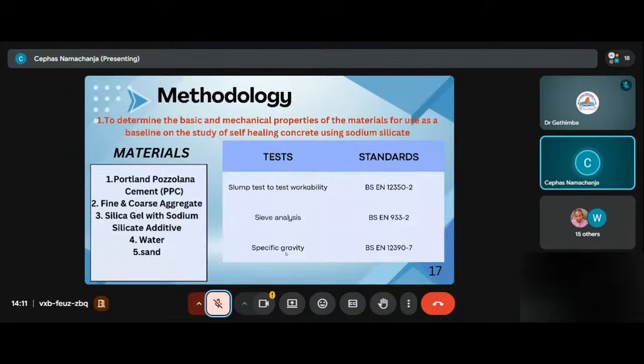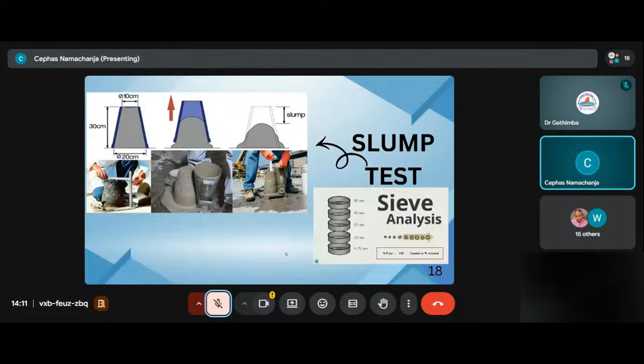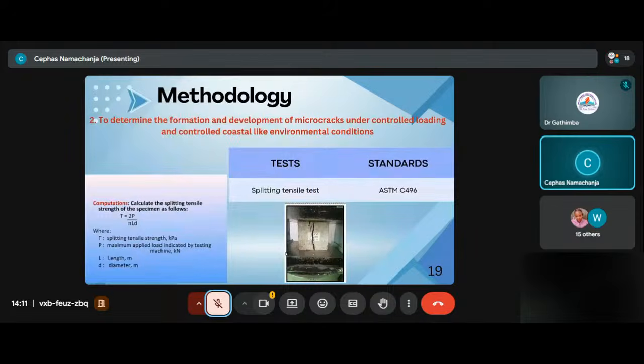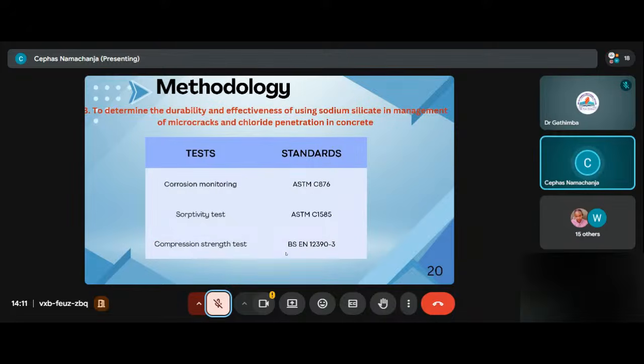Methodology, based on our first objective, we're going to conduct slump tests to test the workability of the materials, sieve analysis, and specific gravity according to the standards. This is the total test we perform. Based on our second objective, we're going to conduct a splitting tensile test to induce the crack. Based on our third objective, for durability, we're going to conduct corrosion monitoring, sorptivity test, and compression strength test.